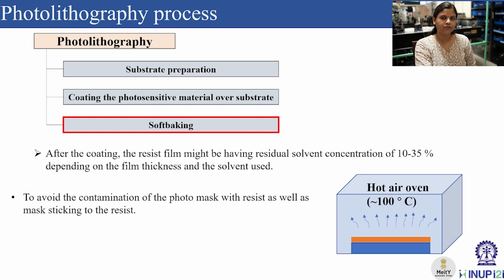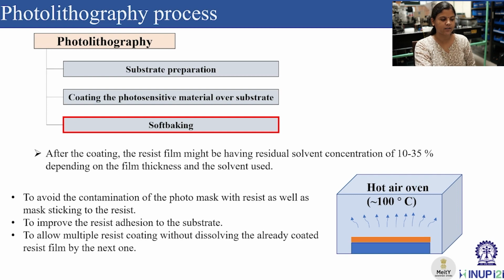Now, what is the benefit of this actually? We use it in order to avoid the contamination of the photo mask with the resist as well as mask sticking to the resist, to improve the resist adhesion to the substrate, to allow multiple resist coatings without dissolving the already coated resist film by the next one, and also to increase the stability of the resist structure.